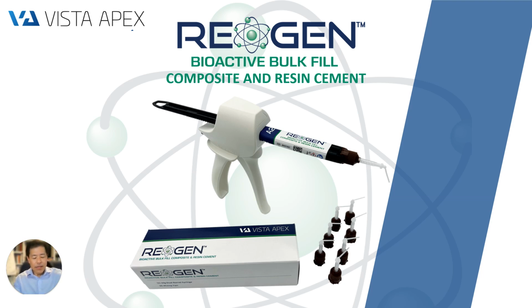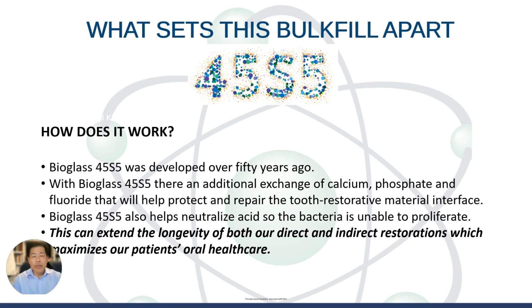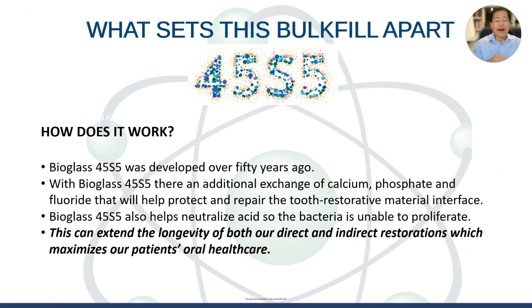And what makes it stand out is that bioactivity, because we all know there's a plethora of bulk fill materials out there, but none of them have that bioactivity. Once again, the Bioglass 45S5, which was developed over 50 years ago, when you put Bioglass 45S5 into the body, it actually creates hydroxyapatite. And so if they put Bioglass 45S5 on a bone, that ceramic turns into bone that cannot be taken off. I mean, it actually grows bone. So you have this additional exchange of calcium phosphate and, in the oral cavity, fluoride that helps to protect our restorations, our teeth, and helps to maintain that tooth restorative material interface.